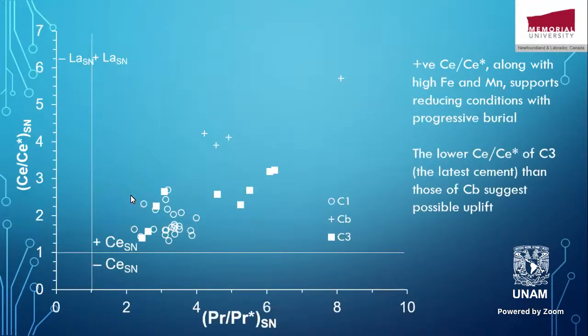Okay, this is again the cerium anomaly here, the positive cerium anomaly, along with the iron and the manganese. Their behavior supports reducing conditions with progressive burial and even dysoxic conditions, not very oxic conditions during the precipitation. And the lower cerium anomaly of the C3, which is the latest cement, than those of Cb and the other ones, suggests the possible uplift.